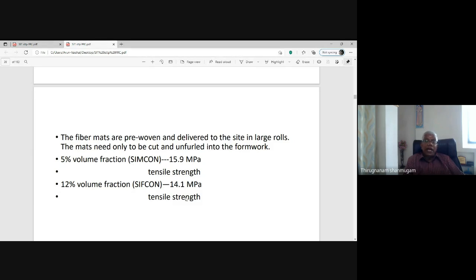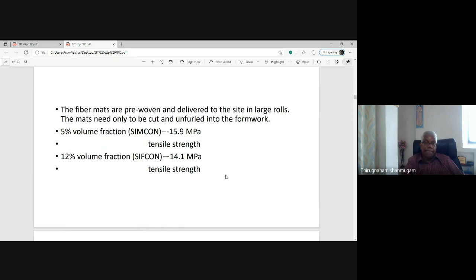A 5% volume fraction in SIMCON produces around 16 Newton per mm² as the direct tensile strength, whereas a 12% volume fraction of fibers is needed in the SIFCON casting technique, and it produces about 14 Newton per mm² direct tensile strength. So 5% is sufficient for producing the required tensile strength, whereas you need 12%, more than twice the volume fraction, in the SIFCON casting technique. So if the steel fiber mat is available, you can go for SIMCON. There is a very good research opportunity in doing research on SIFCON material.